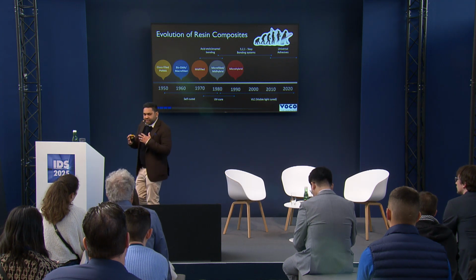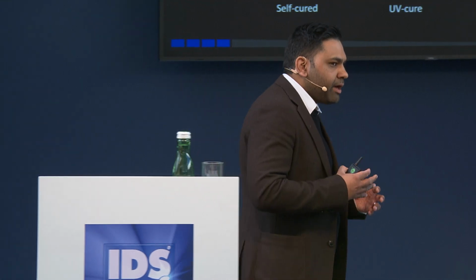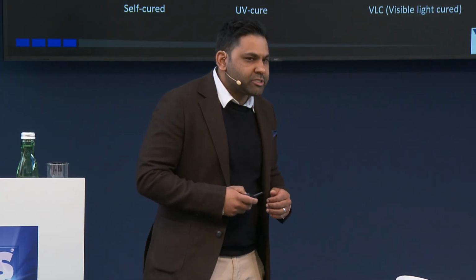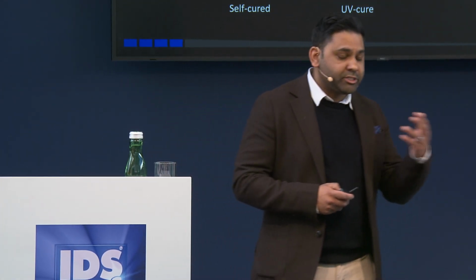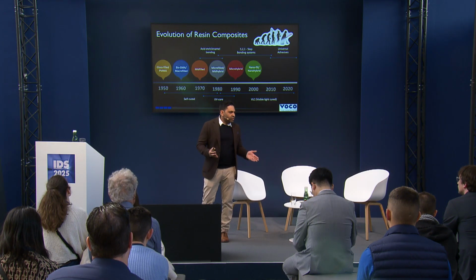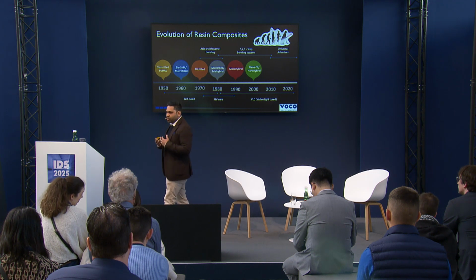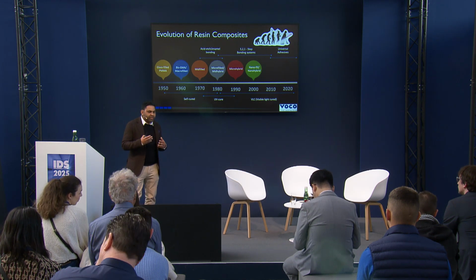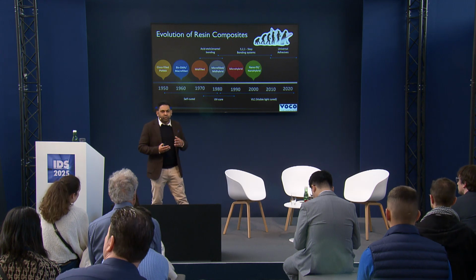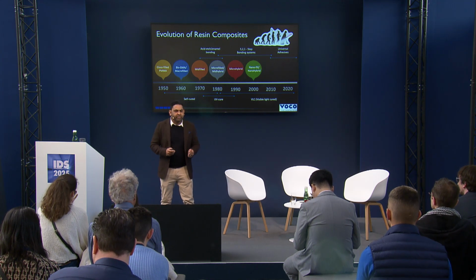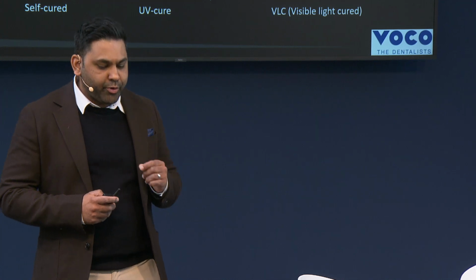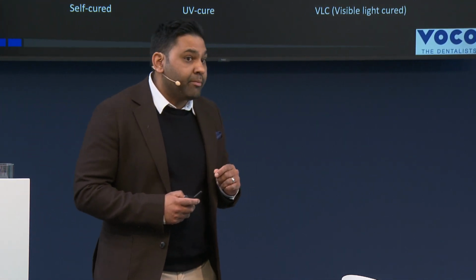So this started to meet the demands of the practitioner much more, having more advantageous properties, better wear resistance, much more fracture resistance, better in load. Also some improvements in aesthetics, whether we're using it posteriorly or anteriorly. But again, the real breakthrough was nanotechnology. In the millennium, we started to be able to really control the filler particle size and move to between 5 and 75 nanometers. And this was a huge breakthrough and allowed us to get much closer to a universal restoration.